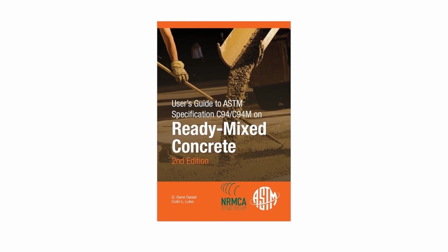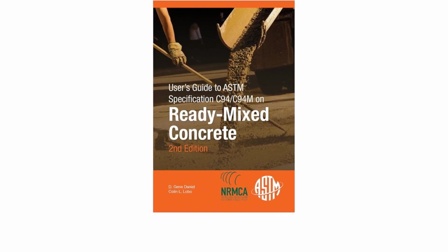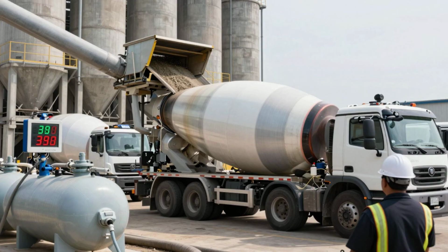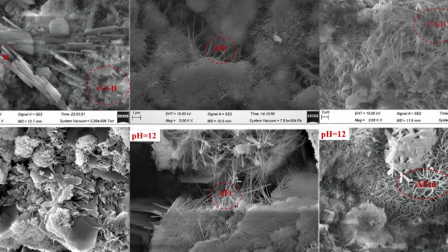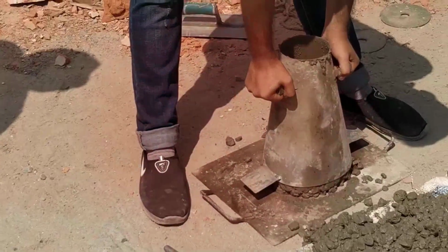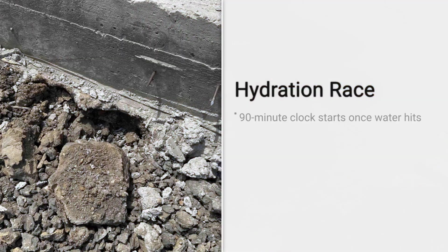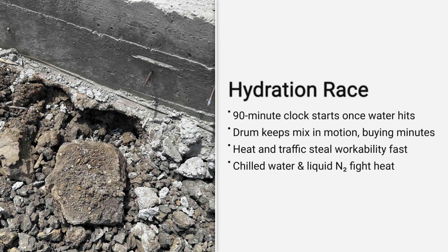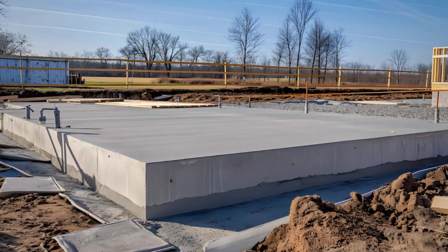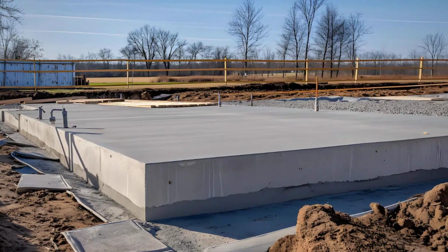This is what the 90-minute ASTM limit is actually measuring, not when the concrete is mixed, but how much hydration has accumulated. At 90 minutes in normal conditions, the crystal network has grown enough that the concrete has lost meaningful workability. It will not flow correctly, will not consolidate properly, and will not bond to reinforcing steel the way it needs to. Pour it anyway, and you have built something that looks like a foundation, but is structurally compromised in ways you will not discover until it cracks.